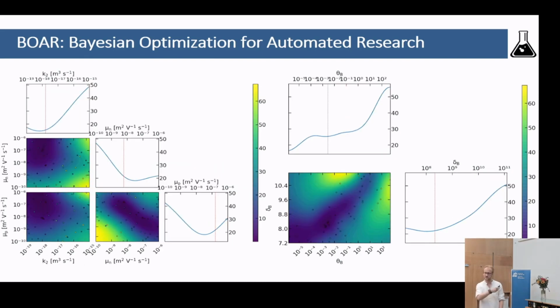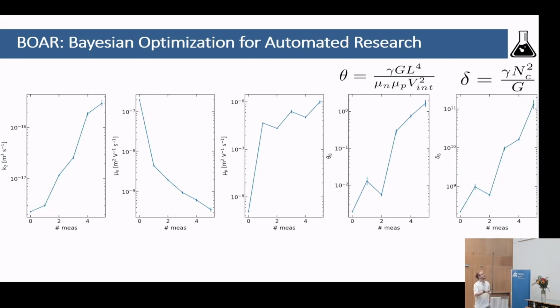And I've tried this on experimental data with a bit more fitting parameters, and I can get results as good, if not better, than presented before, but a lot quicker. Instead of needing a full night on a big workstation, I can get this in maybe 10 minutes. And then at the end you can make graphs like this where you see the evolution of the different parameters. Here it's just the number of measurements in time. And what's nice with doing that with Bayesian optimization and Gaussian process is that you can also get some error bars on the parameters that you estimate.